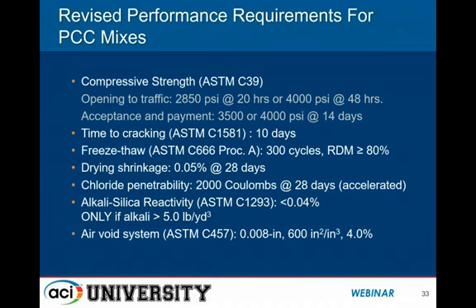Chloride penetrability was also specified, but this is also for long-term durability, and it also allows us to get a sense for how the long-term corrosion behavior is going to potentially affect us. And provided you can prevent the cracks from occurring, we can get significantly long life expectancy out of these patching systems. With the type of chloride resistance that we are getting, and in conjunction with mitigation of cracking, we're expecting the life of the patches made under this program to exceed 30, 40 years under the current expectation for tollway salt loading. So really outstanding performance that I believe they're going to be getting over the long run.